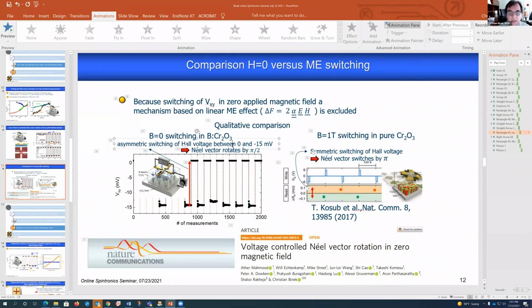It's a 90 degree rotation. What is important also to stress here, the thing that immediately follows from the fact that we do this without a magnetic field, the one thing is clear. The switching, whatever it is, I repeat, is not switching based on the linear magnetoelectric effect as we know it from chromia. That's not what it is, right? That's why I presented this explanation in terms of polarization, strain, change in anisotropy, and then change of easy axis due to change in anisotropy.